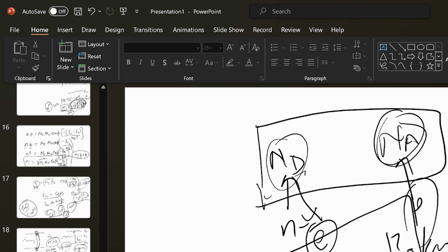So this is 10 raised to power 7, but we want to make a diode with the PN junction. So what we will do is we will cover this surface with oxide or with some photoresist through lithography. We will do that, and we will dope this one with the P type, with the boron, and we will remove this one later.